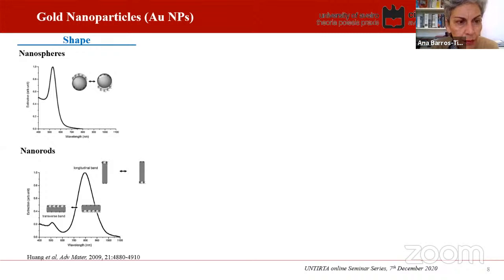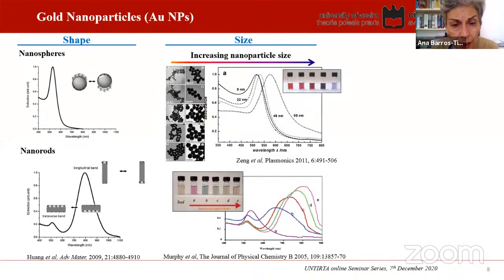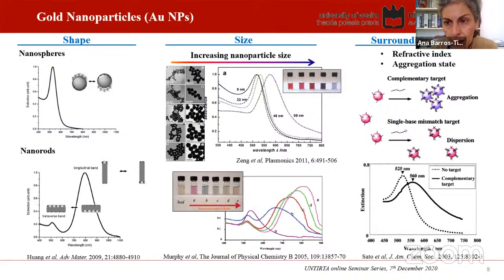Now, as you well know, gold nanoparticles can vary a lot. We can have nanospheres, we can have nanorods. Also, they can have different sizes depending on the reaction conditions we choose. We can tune all of these. And finally, depending on the medium they are in, they will have different wavelengths at which they absorb. So it depends on the surrounding medium, on the refractive index, the aggregation state resulting from that, as well as the presence of complementary targets that lead to the aggregation or not, and therefore to a shift of the plasmon signal.